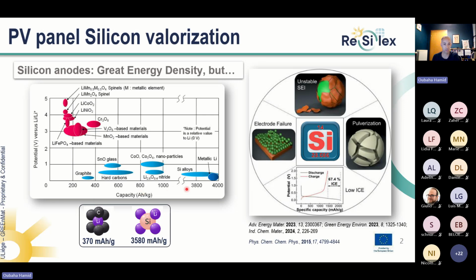However, silicon has some drawbacks. Actually, silicon is so good in storing lithium that the volume of the particles can expand by up to 300% during the lithiation, and this shrinking and expansion of the particles can lead to the pulverization and failure of the electrodes. So the key is to find a way to stabilize these silicon particles when they are used for lithium storage.